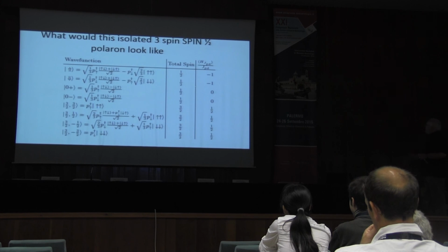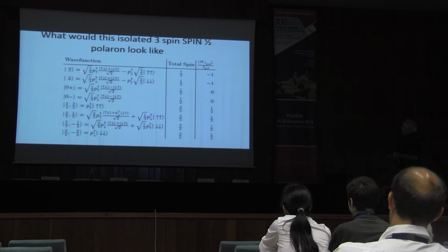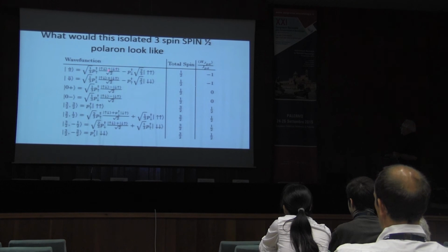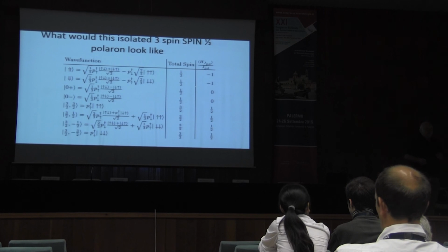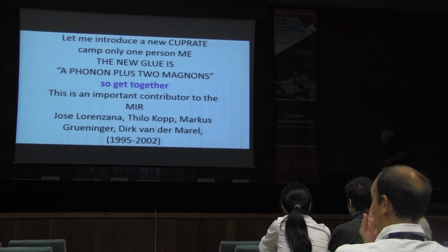The eigenstate of this simple isolated problem looks like this. It has singlet states or spin up, spin down states for the 2 coppers. This is for the oxygen hole being spin up, and one copper spin up and the other copper spin down. But notice the plus sign. It's a ferro component, a spin triplet phase rather than a singlet phase. And the net spin is a half, and the energy is at -1 times the absolute value of J. So it's a very large energy scale that stabilizes this particular state.